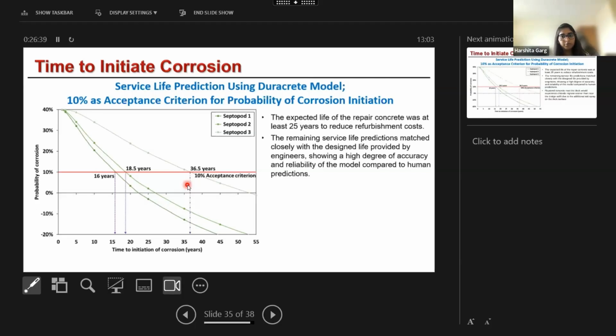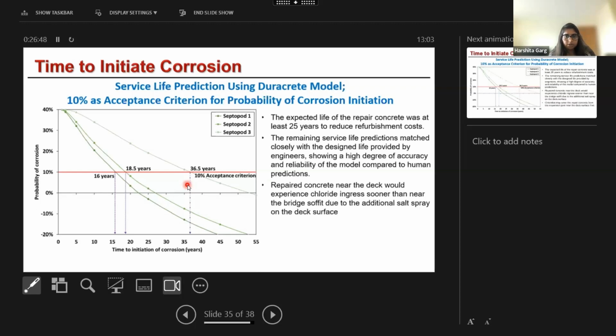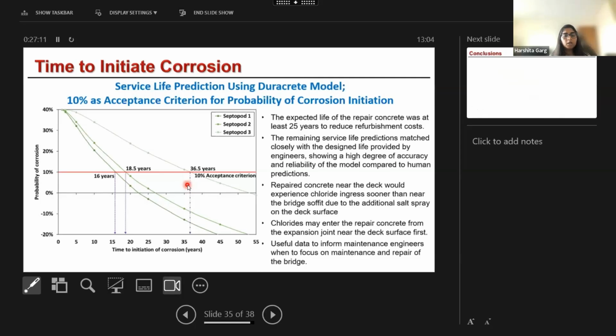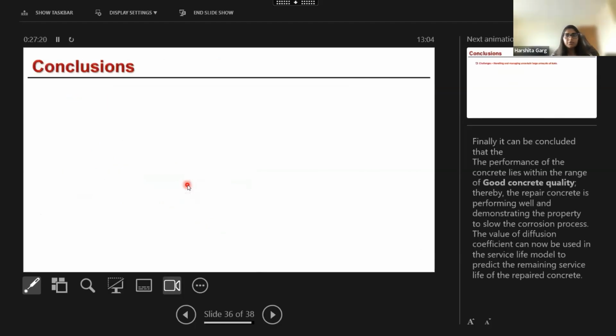So the remaining service life was predicted quite closely, which shows a high degree of accuracy and reliability of the model compared to human predictions. It also identified that the repaired concrete near the deck would experience chloride ingress sooner than the bridge soffit due to additional salt spray on the deck surface. And finally, the chlorides may start to enter near the expansion joint near the deck surface first. So all this information is quite useful to inform maintenance engineers when to focus on maintenance and repairs of the bridge. So finally, conclusions.